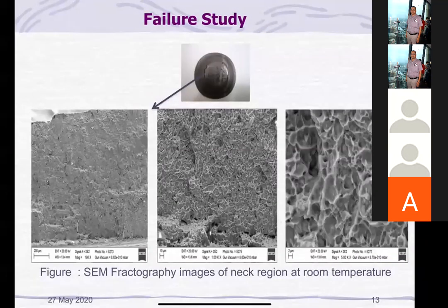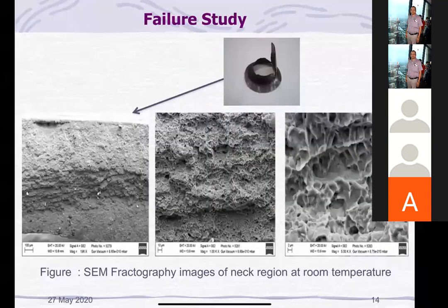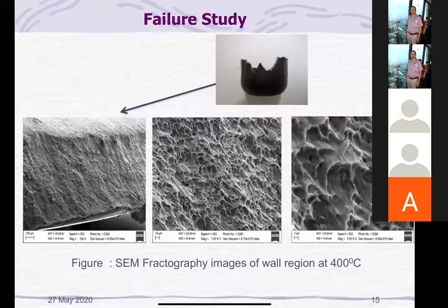Okay, now? So failure study also we have done. At room temperature, of course, it shows a ductile fracture because there are dimples here and all that. But somewhat you can say it is a brittle neck region. And at 400 degrees centigrade, see, the fractography is somewhat ductile.